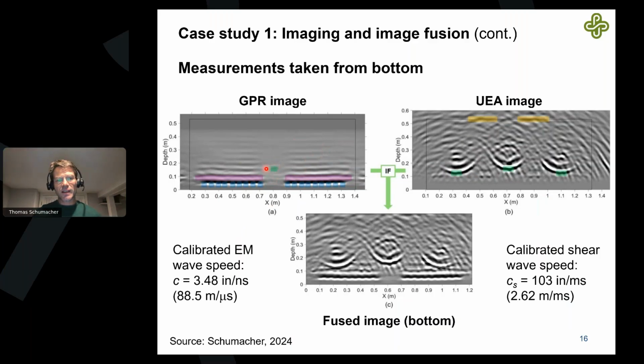We did also see a teeny little dark reflector here, which we were thinking might be associated with the void. The ultrasonic echo array image very clearly showed these voids. That was very nice to see. So indeed, this is a voided slab, it turns out. Between the voids, we could also see the top of the slab, which was very helpful for making sure we assumed the right wave velocity.